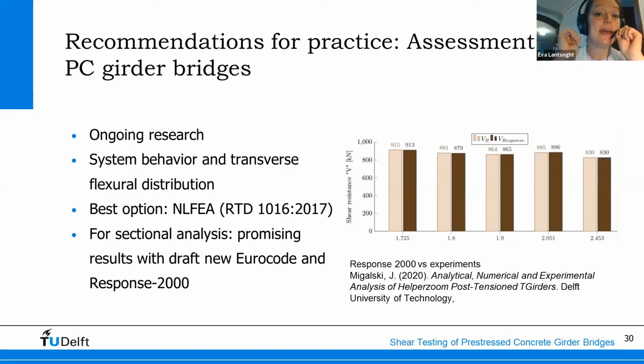We also found that, as I said, in the Netherlands, there's this Dutch guideline for nonlinear finite element analysis, the RTD 1016 from 2017, which, if you follow the guideline, gives good predictions of the experiments, and so that could be used for assessments. And one of our master students was looking at the draft new Eurocode, and he found that there were some promising results when using the draft new Eurocode as well as Response 2000.